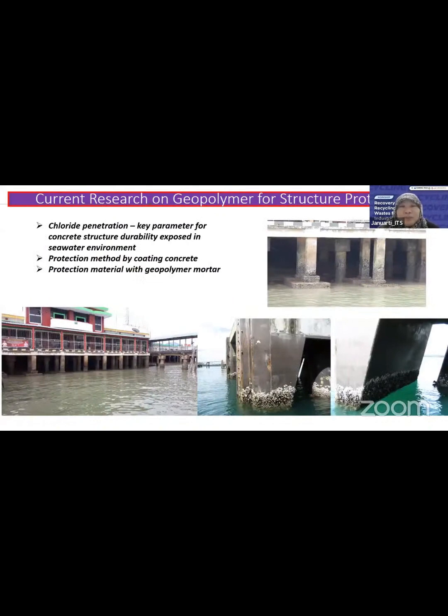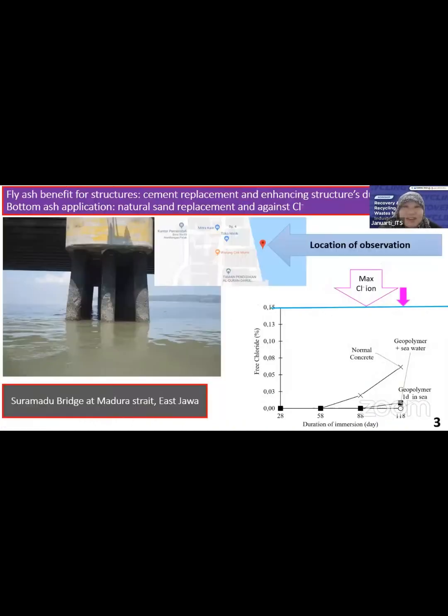And this is one of the pictures we took from Tanjung Balai Karimun, one of the islands very near to Riau Island. And we can see here that these piles have a lot of corrosions. We can also capture here a lot of barnacles. We call it biofouling. It's a very common phenomena in the beach and also in the coastline. And corrosion will occur not only because of the chloride ion, but also the attack of the barnacles. So what should we do with this structure?